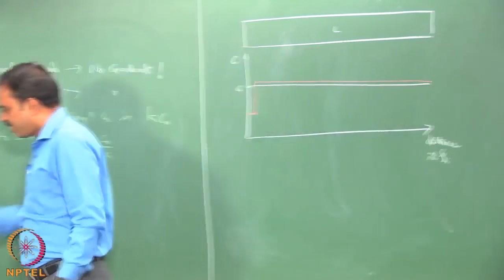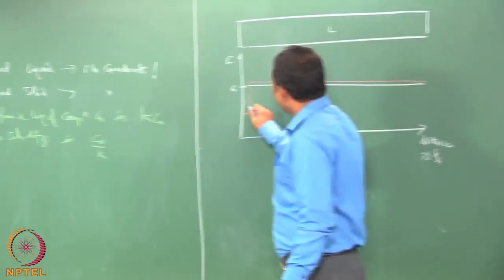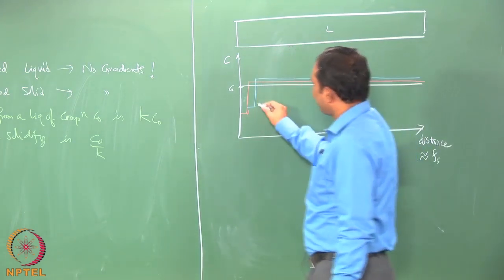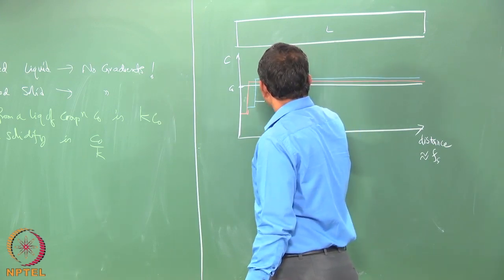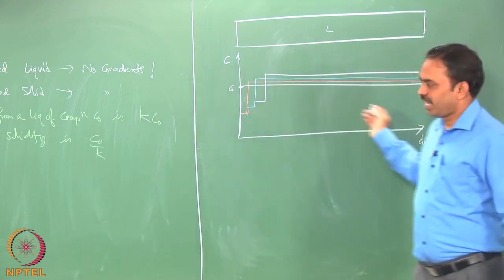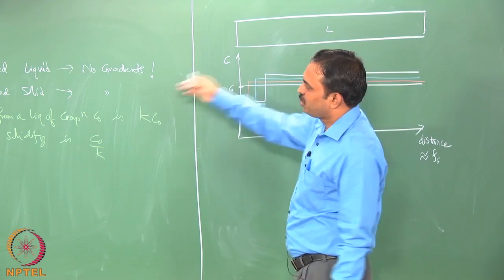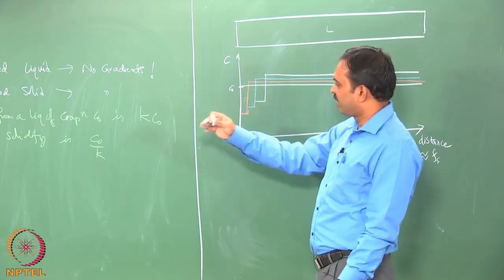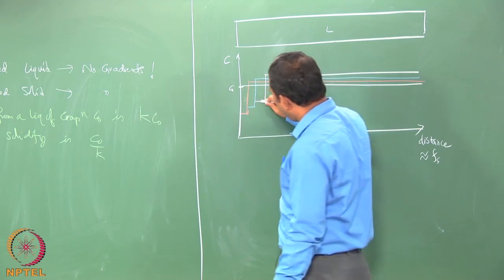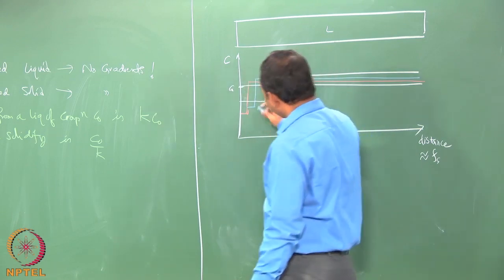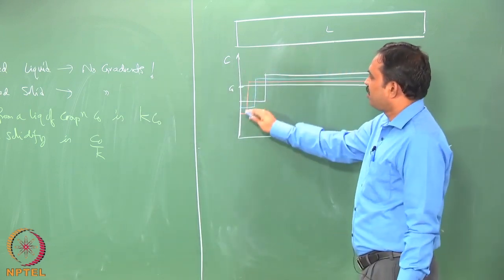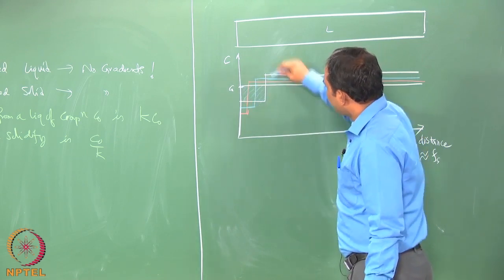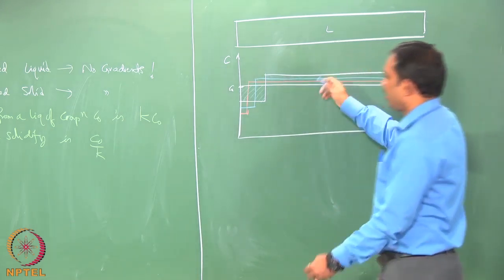If you then solidify another 5%, it would dump some more, and solidify another 5%, and it can keep going like that. When we assume that this region is fully mixed, it means that within the solid, these kinds of steps are not allowed, since it is fully mixed. Therefore, we would just draw them all the way to the end. Every time, the composition of the solid is adjusting, and the solute in this box is distributed on the other end, so that it can be balanced.